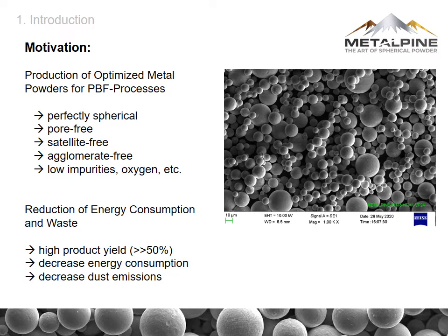What is the motivation of our work? We have developed this new process to produce optimized metal powders for powder bed fusion processes, with the goal to produce perfectly spherical powders which are pore-free, satellite-free, and agglomerate-free. As we are using a crucible-free process, we expected low impurities and low oxygen content. At the same time, METALPINE committed to the 17 Sustainable Development Goals of the United Nations. So we try to reduce energy consumption and waste, and also decrease dust emissions as we are operating in the middle of a town.